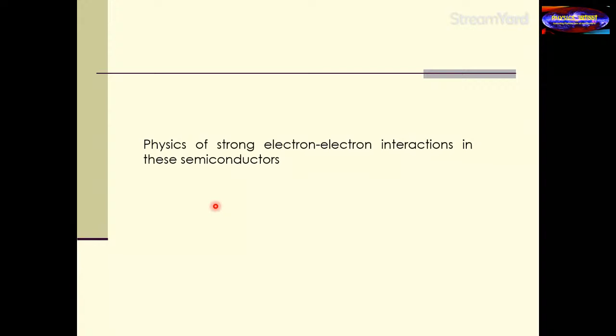So the question is the band. I showed you a plot of the band dispersions for MoSe2, and that was calculated assuming an independent electron approximation, which is effectively saying that I consider all the electrons around me to be creating an effective field, okay? And this single electron moves in this field. So in this approximation, I'm not considering the Coulomb interactions between the different electrons exactly, but I'm just saying that the rest of the electrons are creating an effective electric field, which this electron sees and interacts with. So this kind of picture loses out on strong electron-electron interactions.